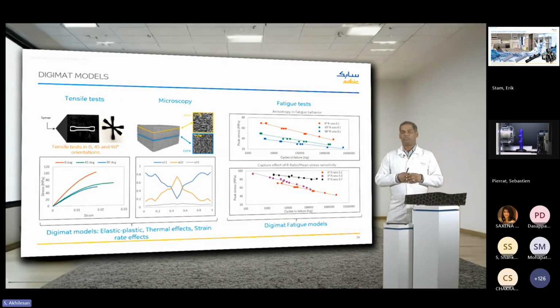In order to capture fatigue, you have to capture at least fatigue data at 3 orientations, just like with the tensile orientation, 0, 45, and 90. In order to further improve the accuracy of the model, you could perform additional tests at various R ratios in order to capture mean stress sensitivity in the model. This results in a better quality fatigue data.